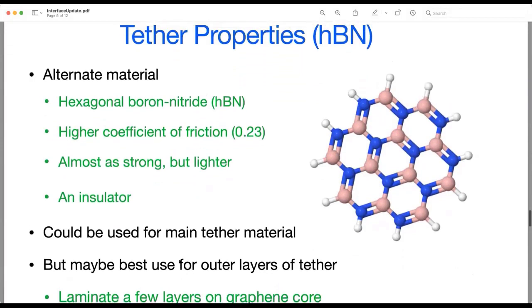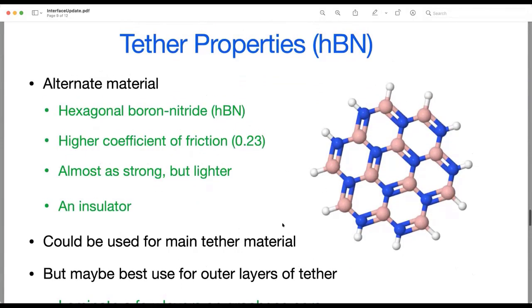Now, another material is hexagonal boron nitride. So you can see a picture here with the blue being the nitrogen and the pink being the boron. So pretty much the same design or same structure as single crystal graphene, except you have different elements. And it has a big advantage of this material. It has a much higher coefficient of friction, so about 0.23. It's almost as strong as single crystal graphene, but a little bit lighter.